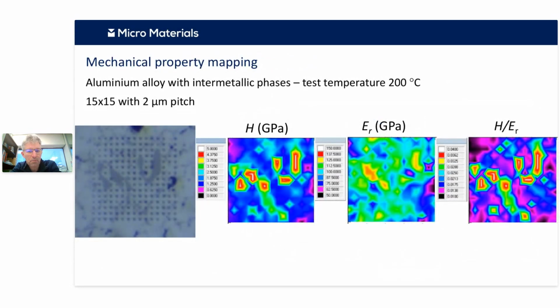So one thing that we're working on at the moment in collaboration with a university in Canada is micromechanical mapping at high temperatures, indentation mapping at high temperatures. This is just an example here at 200 degrees Celsius where we're doing very small indentations into a multi-phase alloy which has these intermetallic phases in, and we can track quantitatively how the temperature dependence of the mechanical properties of the different phases in that material varies by producing these array maps.